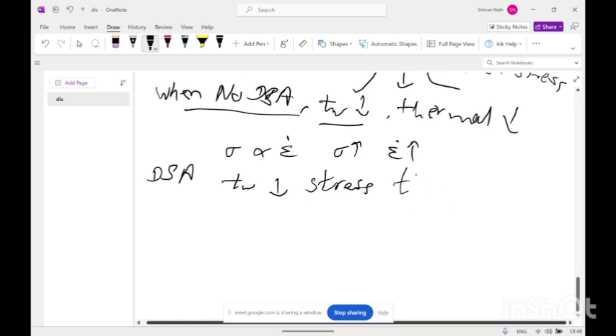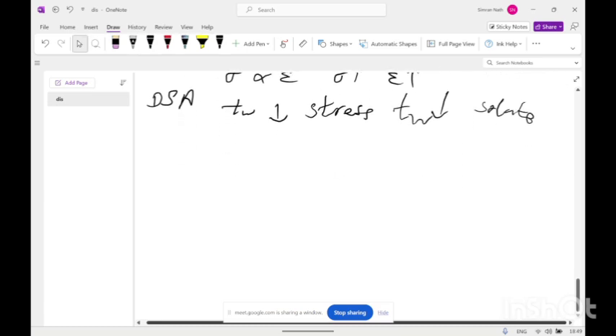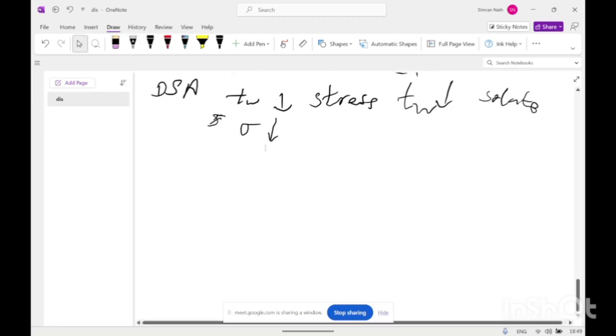So as the waiting time is less, the solute atoms cannot diffuse to the dislocation, and the pinning is less. So because of this, stress will decrease in the dynamic strain aging process.